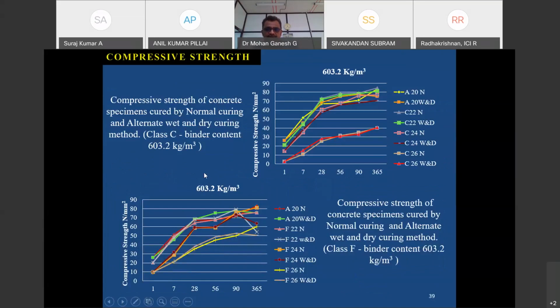Now this is one graph which shows the compressive strength of concrete. Here, this is class C, that is high volume fly ash or Neyveli lignite fly ash, 603 kg. It's a high binder content. 360 or 450 is a normal range, but here we want to get high strength concrete. So for that, we went for the higher binder content. So the compressive strength is around 80 MPa after 365 days curing. You see the graph, how it behaves, how the strength is obtained.